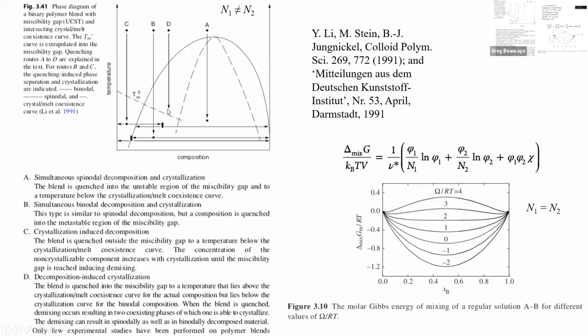So in order to grow the phase, you have to overcome an energy barrier in that part and then grow the phase. It'll go to the binodal compositions. Same thing, the spinodal will go to the binodal compositions, but the mechanism will be different. Right, so spinodal, because it's spontaneous, you get composition growth up a concentration gradient.